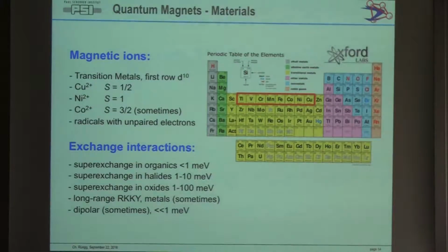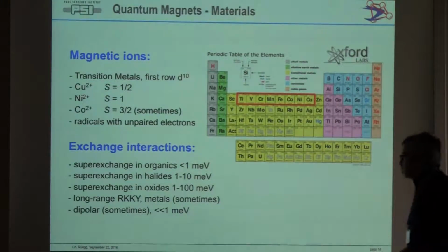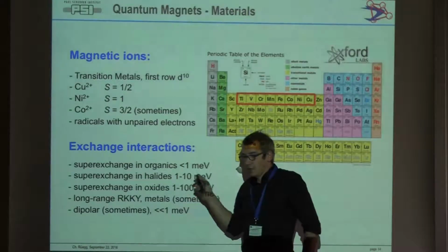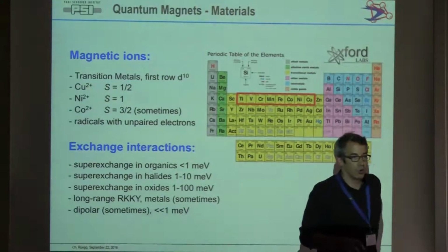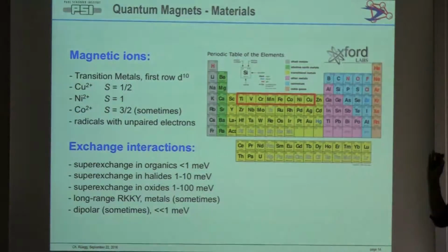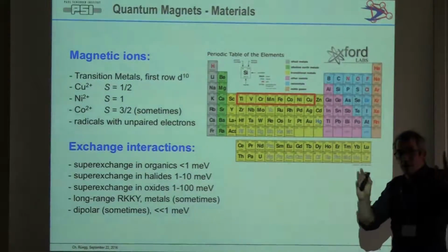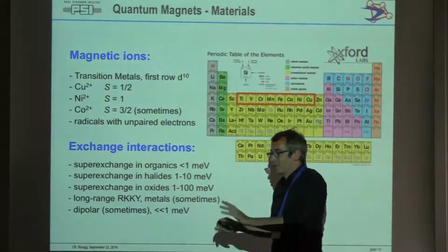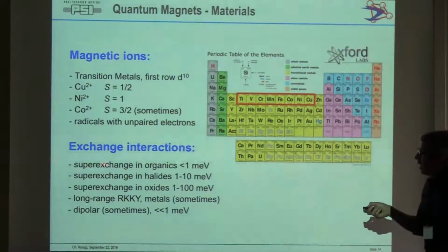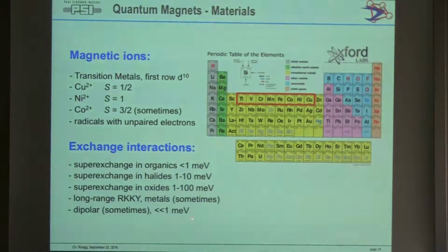So exchange interactions, if you look at the examples from this morning: for oxides, it typically goes from 1 to a few hundred millielectron volts. For the cuprates, it's several hundred millielectron volts. You can have halides, where you go down. I show an example which is just above my boundaries, but roughly the ballpark is this. And organics can be a millielectron volt or lower. Then you have other types of exchange as well.